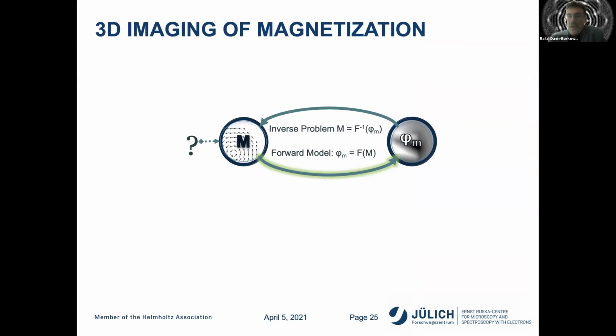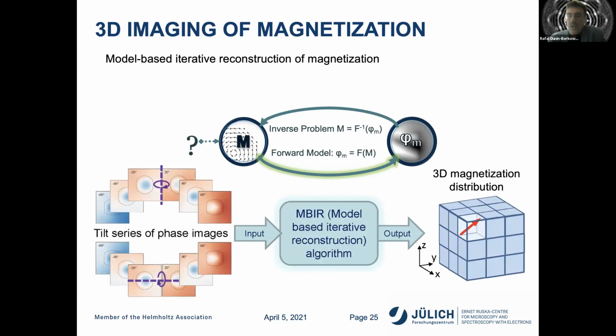The reconstruction of the magnetization M is a whole different problem. It's an inverse problem. And I just wanted to mention briefly that this is a problem which we are tackling in a different way, not by reconstructing the components of B separately, but by using model-based iterative reconstruction of the magnetization, effectively by guessing the 3-dimensional distribution of magnetization, and altering that guess for the 3-dimensional magnetization until it matches an experimental set of magnetic phase images.